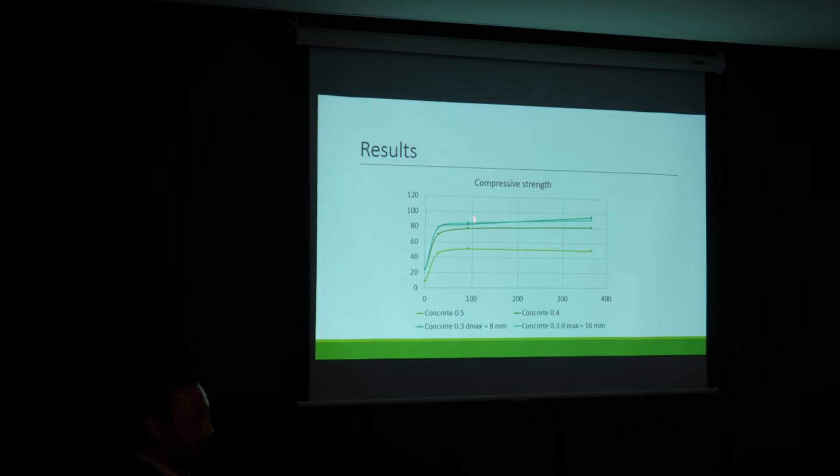Then we made a decision to start after 3 months. And you see that after this time it is not changing so much, because the experimental program for fatigue takes, for example, 2 or 3 months. If we said, okay, we would like to start at 28 days, we have this curve for approximation to use, and then recalculate every point to 28 days.